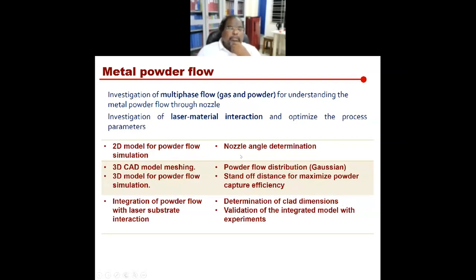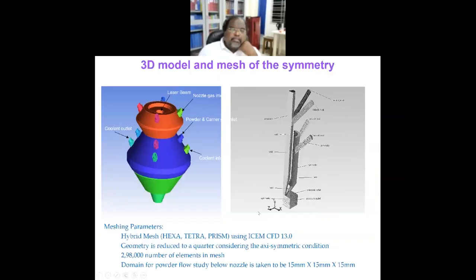So the purpose was that with the first model, the 2D model of powder flow, we should be able to find out the nozzle angle. Second, we did some further studies on powder flow, which will give the powder flow distribution and standoff distance for maximizing the powder capture efficiency. And third, of course, is the determination of clad dimensions and validation of the integrated model with the experiment. So that is the thing.